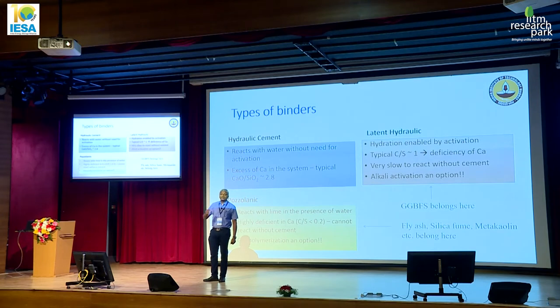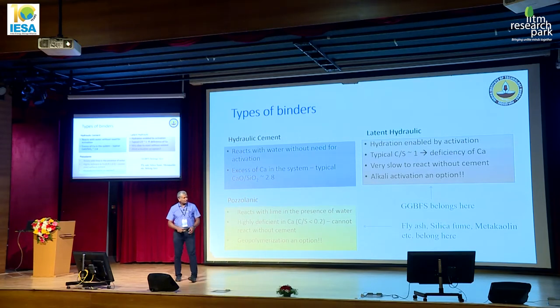It needs the presence of lime. Now, lime is generated during cement hydration. That's what makes it pozzolanic. These binders react with lime during the process of hydration. But this reaction can go on for a very long time. So when we start using supplementary materials, your concrete can continue to gain strength and durability as the age goes along.